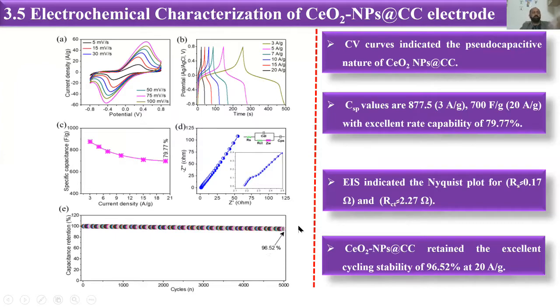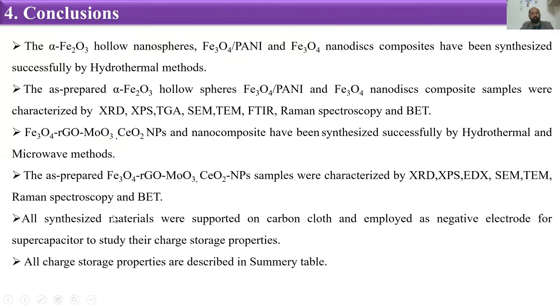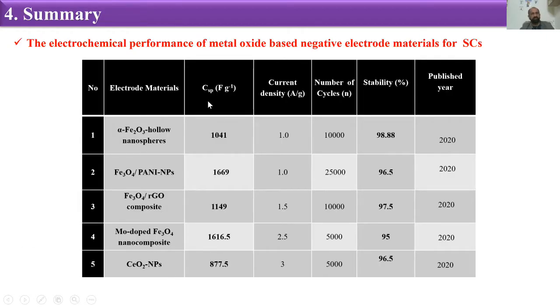So this is all about it. We have done the iron oxide nanoparticles, the Fe3O4 nanoparticles, and the Fe3O4 RGO composite, and we synthesized all these materials by hydrothermal and microwave synthesis methods. So here is the chart summary of our synthesized materials. For alpha Fe2O3 hollow nanospheres, we have this specific capacitance, with the number of cycles and the stability we have attained.